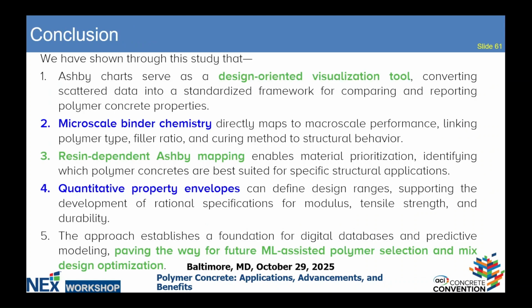Thank you very much. And in conclusion, I would say that the Ashby chart has really helped, where it's converted scattered data into highly and well-visualized data to make mapping simple. And also, it makes it simple in the second case that you're relating a micro-scale binder chemistry, by the binder to aggregate ratio, to see what is going on in the compressive strength. And also, it allows you to know which polymer binder resin performed the best.